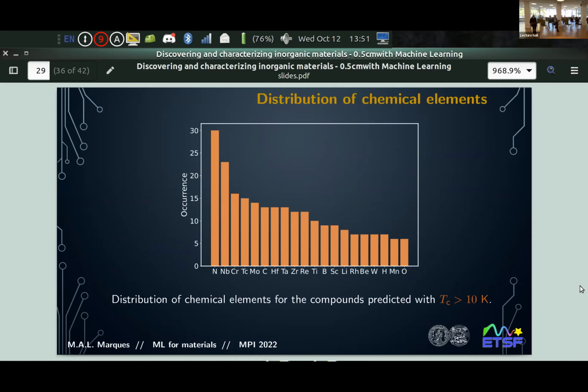First surprise: we grabbed all the results we have with more than 10 Kelvin, and we plotted the distribution of chemical elements. Has anybody guessed this? This apparently is the element that is most correlated with high-temperature conventional superconductivity: nitrogen. I didn't know. And I think no one knows, because it's a complete surprise. Then it's obvious. Niobium, all these transition metals are obvious. Carbon is not a surprise. Transition metals, boron is not a surprise. Hydrogen is here. There's a huge amount of people that are trying to find better superconductors at ambient pressure with hydrogen. Maybe they should look at nitrogen, right? So, nitrides.